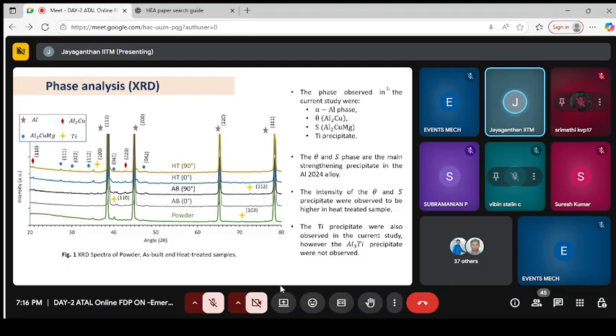That's where we did X-ray diffraction right from the beginning of the powder, and then the as-built 3D printed sample, vertically built being 90 degree, horizontally built being 0 degree, and the heat treatment also we did for both samples. And what is the phase observed? The primary element for this alloy is aluminum, that is being indexed in this X-ray diffraction as alpha phase.